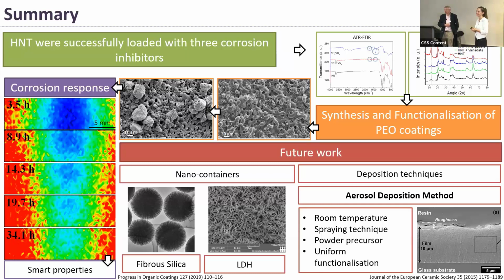Hi, Beatriz. Thanks very much. I was also interested in when you add the inhibitor groups afterwards, after you've made the film and you deposit the structures. That, I suppose, means there's a sort of a lifetime to those things because they're all exposed in sort of open porosity. But would it be possible to actually have another stage where you can seal off some of those locations and encapsulate those inhibitors? Yes, we can apply a further sealing post-treatment that will prevent what Michele was saying before, so that would keep them inside the pores.